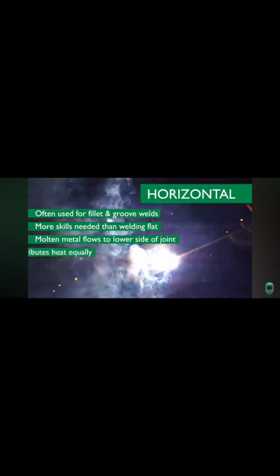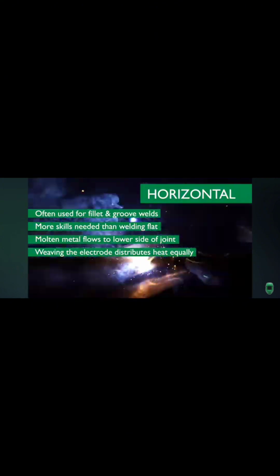Horizontal position. In the horizontal position, the weld is on the upper side of a horizontal surface and against a vertical surface. The axis of a horizontal weld is along the horizontal plane and is often used for fillet welds or groove welds. This type of weld is more difficult than a flat weld. A potential issue for this welding position, which makes it more difficult than a flat weld, is that the molten metal can fall to the lower side of the joint and heat can rise to the upper side. This makes creating a uniform deposit difficult. However, weaving the electrode distributes heat equally and prevents the puddle running down and has the additional benefit of faster freezing.